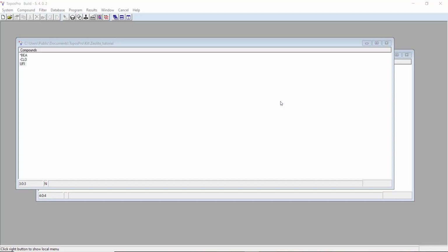So now we can move on to the most complicated case, where you calculate a modified natural tiling for a framework. So why would you want to do this? Let's say, for example, you've calculated your natural tiling for your framework, and you've tried to grow the structure in CrystalGrower, but for some reason your crystal is growing as a very thin plate, like one layer thick. This is due to some situations where you can get very large tiles calculated, and depending on the connectivity of the framework, this can create very large energy barriers towards growth in certain directions.